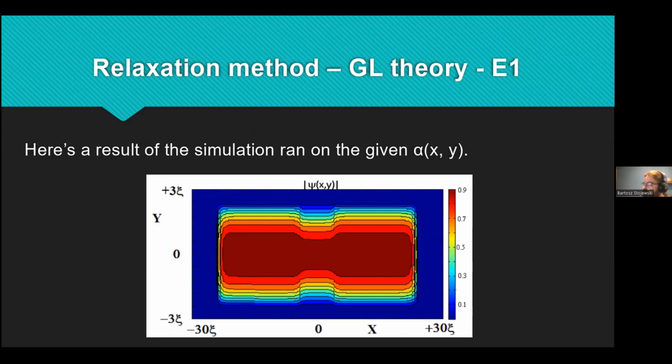The presence of the normal strip reduces the superconducting order parameter, SCOP, in a more significant way than in the case of weakening of the superconductor given in the slide. The diffusion of Cooper pairs from the superconducting strip into the normal strip takes place. In this case, we can see how our simulation shows a possible physical solution for the equation.